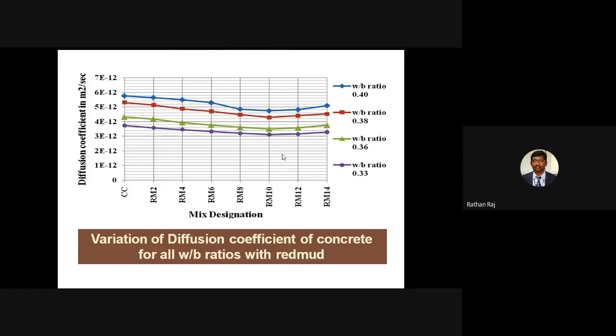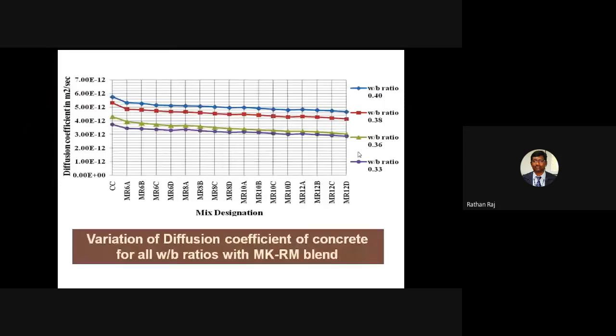So particularly for the combination, this is MR6A, 6B, 6C, 6D. It is showing the 6% replacement of the different proportions, as I already indicated: A indicates 50:50%, B indicates 60:40%, C indicates 70:30%, and D indicates 80:20%. And these are all 8% replacement, 10% replacement, 12% replacement. So in all these replacement levels and all the water binder ratios, the diffusion coefficient is decreasing well. That shows that adding supplementary cementitious material always decreases the diffusion coefficient.